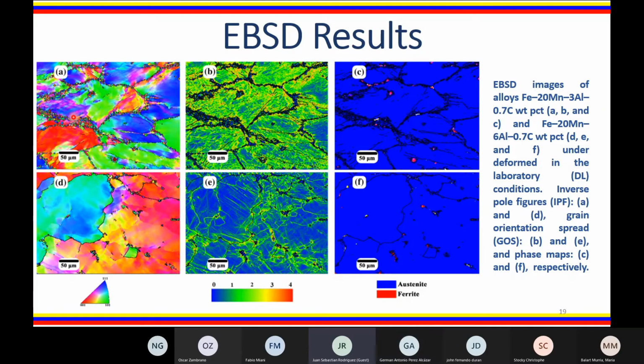Due to the one-step deformation condition, it can be seen that the sample is textured. According to the figure corresponding to grain orientation spread, b and e, there are low degrees of misorientation, which indirectly indicates that they are grains with a low level of dislocation. That is, according to the processing, they are uniform grains. Finally, a phase map is presented, in which a small ferrite formation is evident, but according to Mössbauer and X-ray diffraction, this condition does not have ferrite. It is assumed to be a result of improper data indexing.